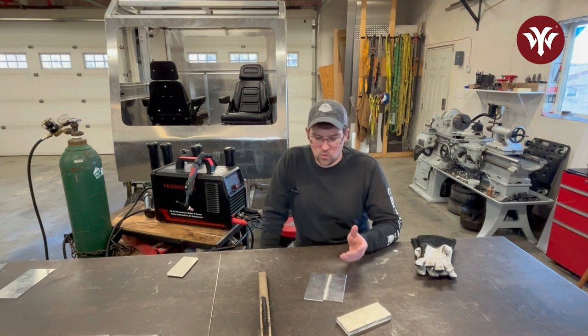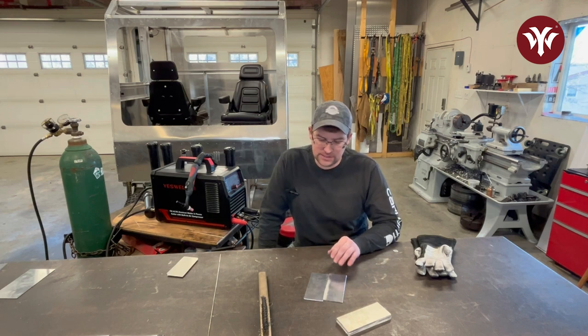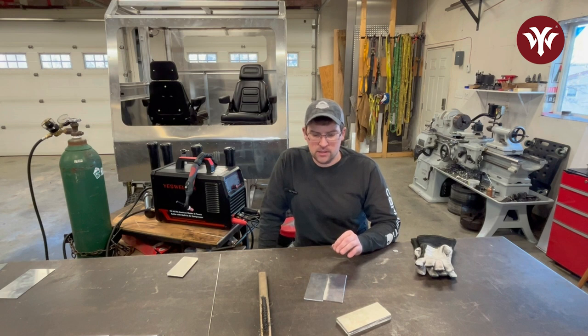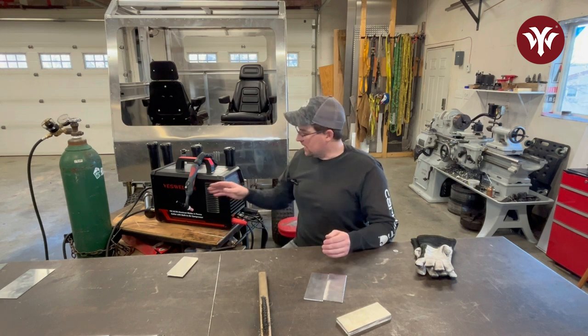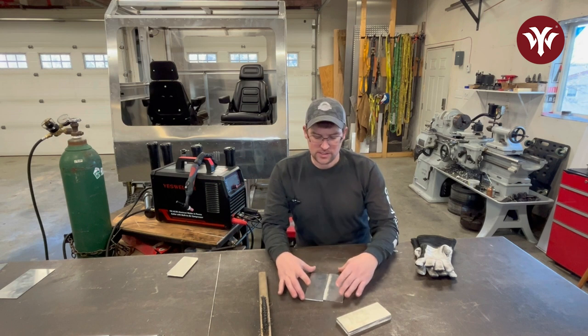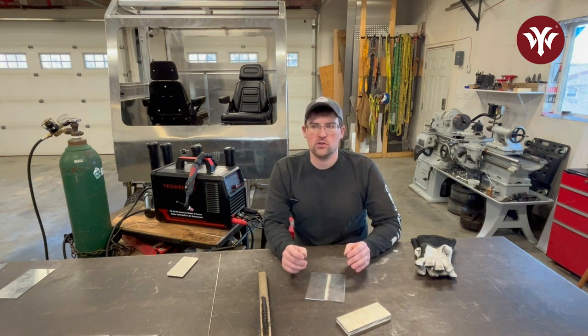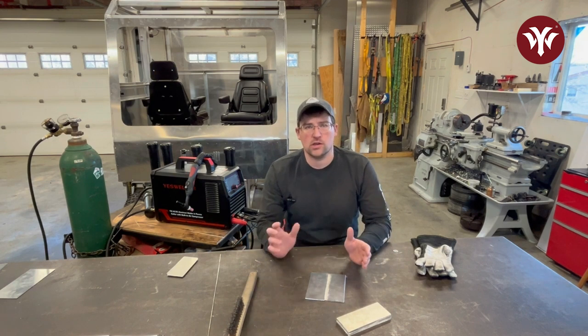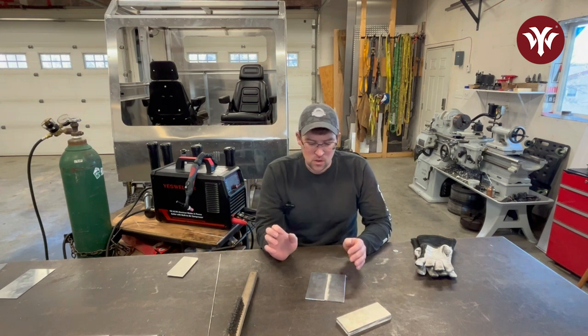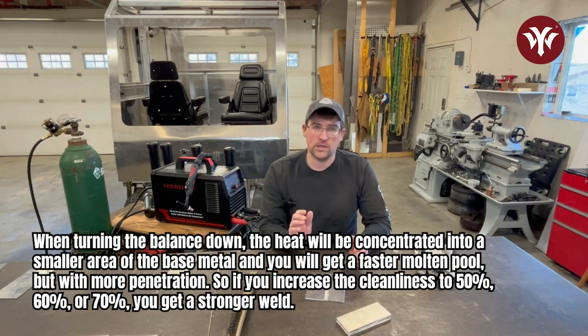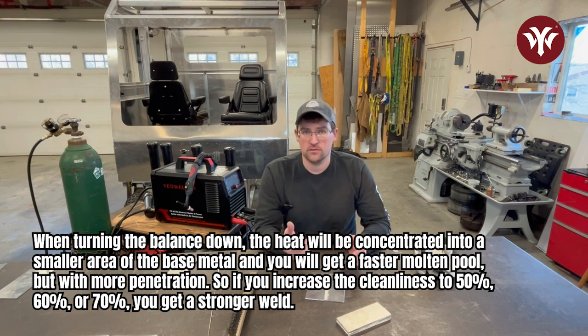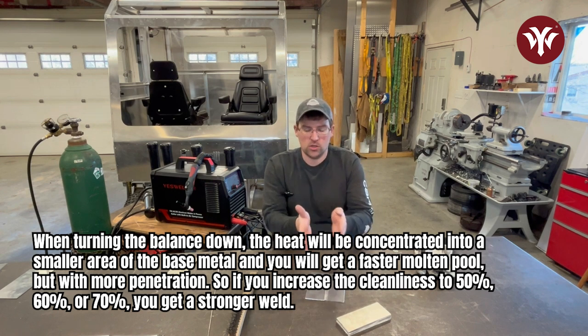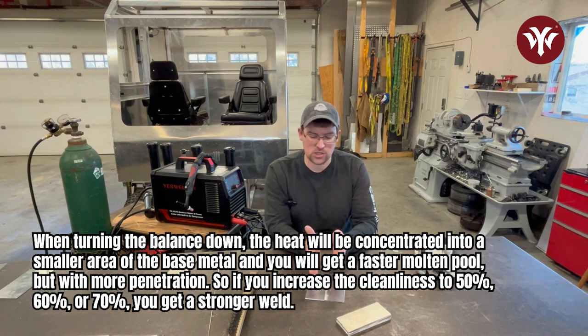Something else I should mention when playing with the balance of your machine is that it's not only playing with the cleaning cycle and where the heat's going in the part, it's also going to affect your penetration. And that's one of the reasons why you also want to try and find the right balance. When you set your balance low, which is very little cleaning action, like 10, 20, 30%, you're going to concentrate that heat to a smaller area in your base metal, which is going to allow you to get probably a faster puddle, but penetrate more.